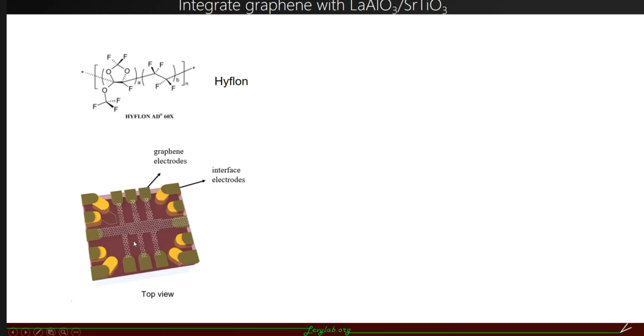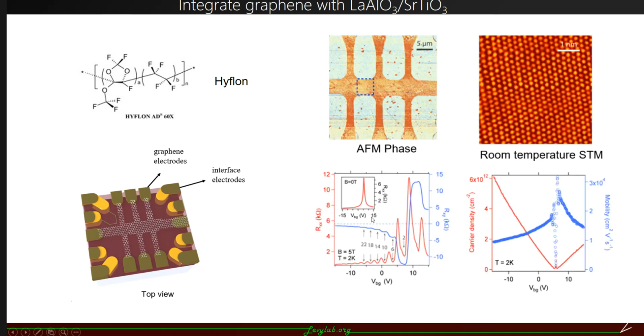And then we use photolithography to pattern the graphene into a Hall-bar structure and make gold contacts to both graphene and interface electrodes. Here are the AFM image and the room temperature STM image, which show that even at the atomic scale, our graphene is still clean. And at 2 Kelvin, we can see the quantized conductance of the graphene. The mobility is also relatively high.